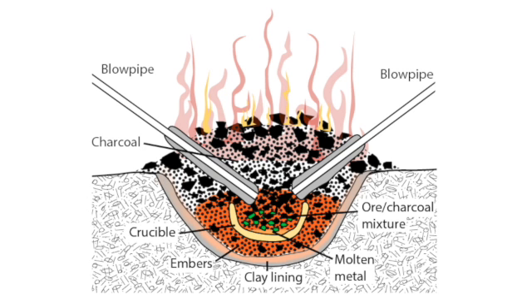In the example of pit smelting of copper, illustrated here, blowing air through the blowpipes, insulated with clay, provides just enough oxygen for the combustion of the charcoal, but it's incomplete combustion, resulting in the release of carbon monoxide. The mineral in the ore decomposes as oxygen from the ore binds with the carbon monoxide to produce carbon dioxide, which is expelled along with water vapor that results from the oxidation of any hydrogen that's in the ore. Later, the metalsmith can remove small pieces of metallic copper that are left in the crucible at the bottom of the pit.